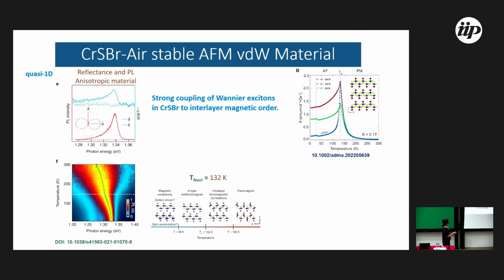And there are two phase transitions in this material. One is the Néel transition, but people observe also another transition, which is under discussion, but it's more related to defects in the crystals. And there is a strong coupling between exciton properties and the magnetic order. We will see this more clearly in other slides. But if you plot, for example, the emission as a function of temperature, this is the color-coded map of the photoluminescence, you can see clear changes at the Néel temperature, and in our case, we can also always see a change at this phase transition related to the defects.